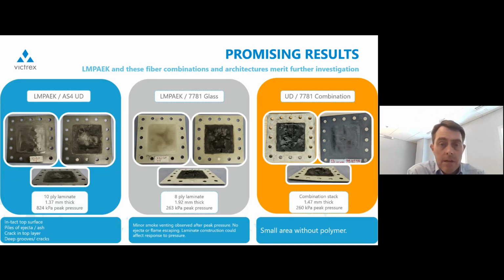So here are a couple of pictures of what they look like after testing. In each image, you see the side visible to us during the test on the left, and then the side that sees the heat on the right. In each one of these you see a bit of charring, and if you could zoom in and look at these or hold them in your hand, you would see some ejecta from the decayed battery embedded in these. So it's a pretty violent, pretty aggressive test.